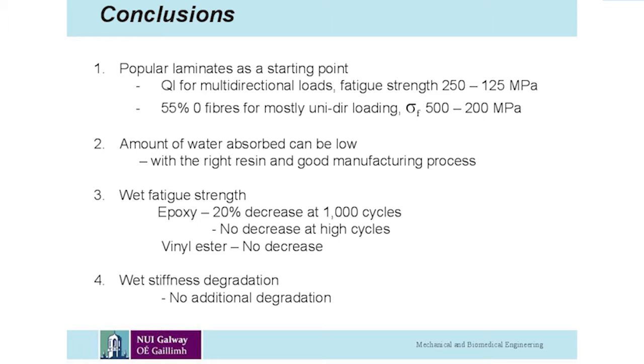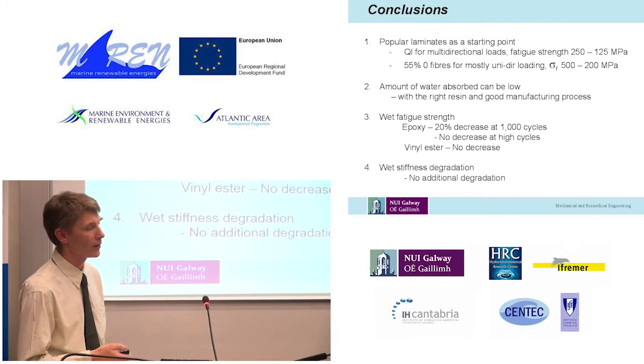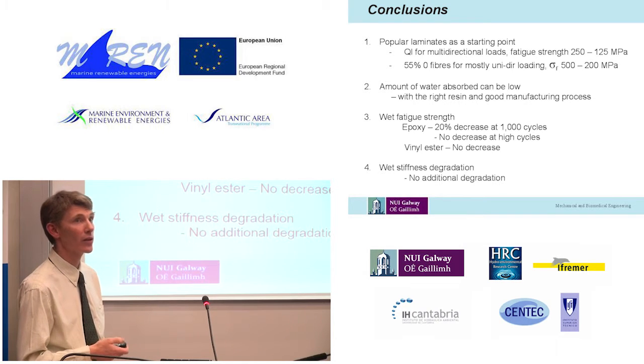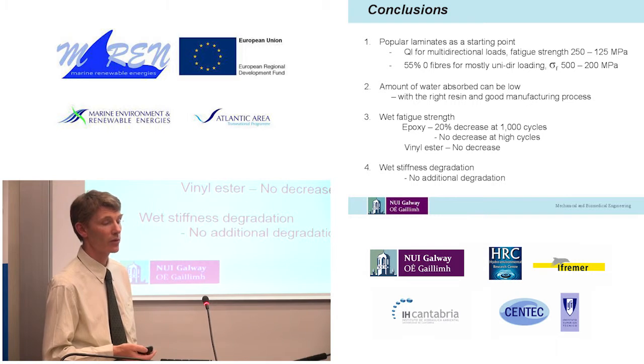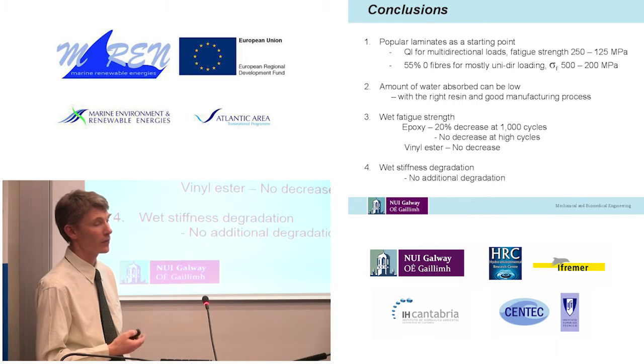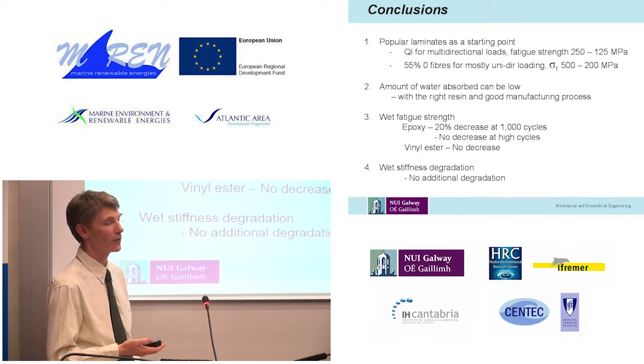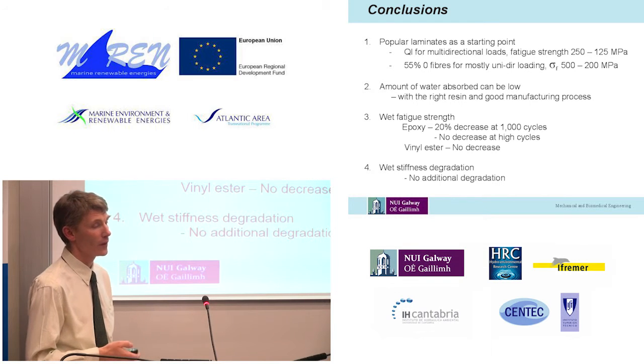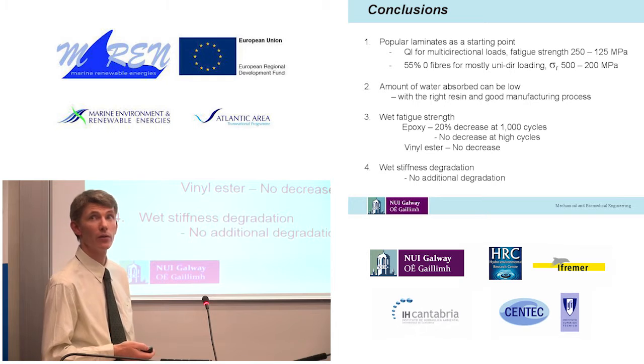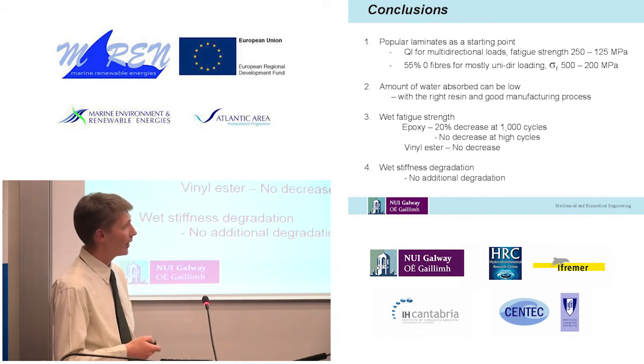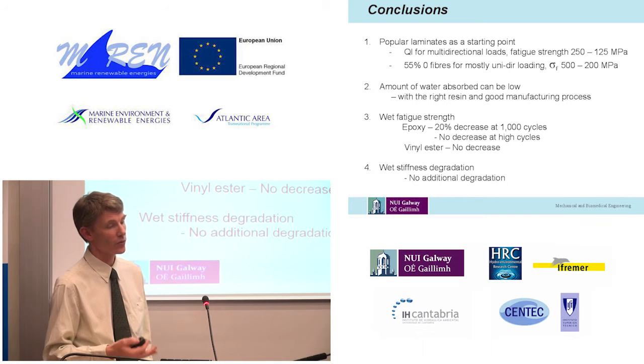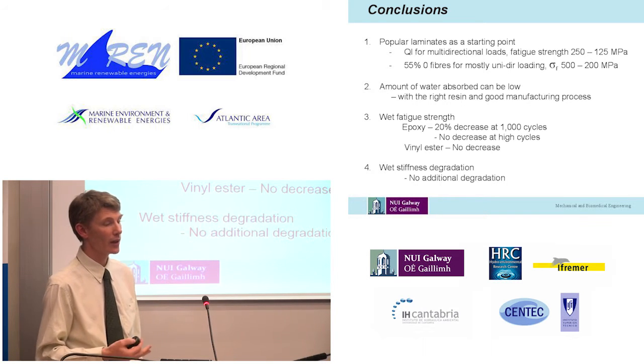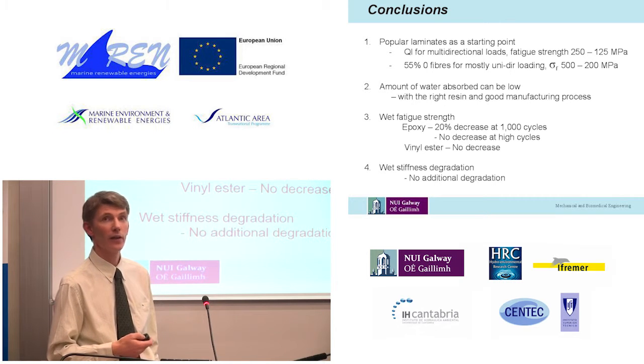So in conclusion then, I've talked about a couple of popular laminates as a starting point for design. The quasi-isotropic material is for multidirectional loads, and that has a fatigue strength between 250 and 125 MPa. For unidirectional loads, if you put about 55% of the fibres in the direction of the primary load, then that has a fatigue strength between 500 and 200 MPa. The other thing is that if you choose the right resin and have a good manufacturing process, you can get the amount of water absorbed to be quite low, and I certainly think that's a good idea.